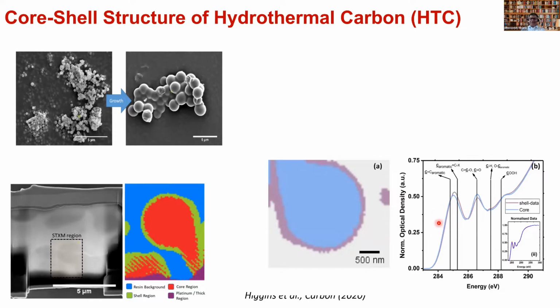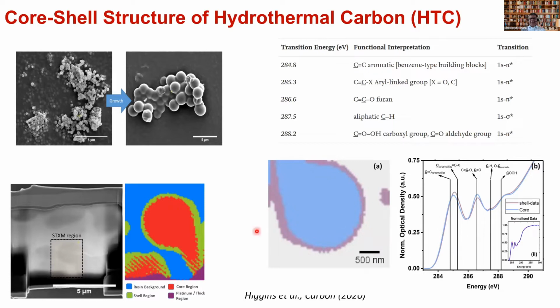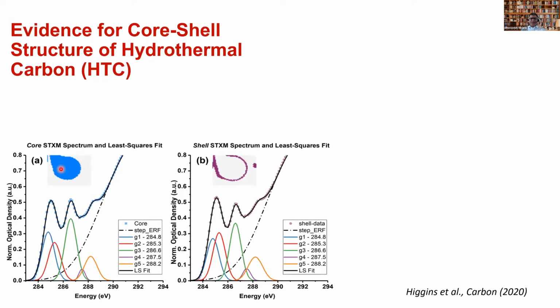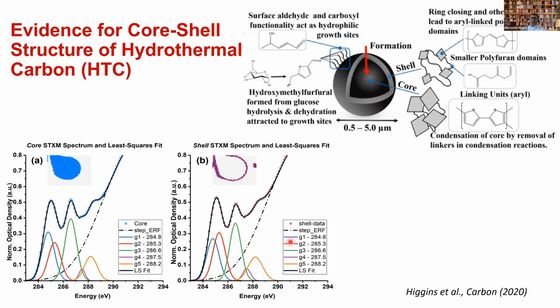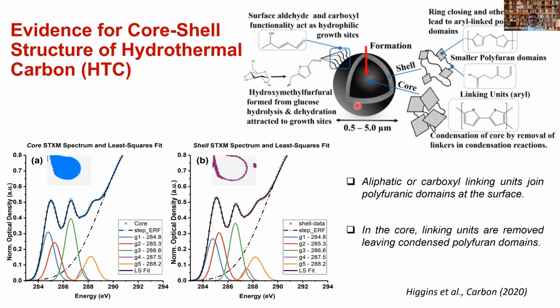Of course, one might say, oh, these are relatively small differences. Of course, in a material which is mostly like 90% carbon, you can't really expect huge differences. But all these differences actually account for some important transitions, as you can see here. More importantly, when we took the core and shell regions and extracted spectra out of those and analyzed them, we found a beautiful picture. The interpretation that came out, in a nutshell, is that aliphatic and carboxyl linking units join polyfuranic domains at the surface, as you can see here. But in the core, linking units are removed, leaving condensed polyfuranic domains. So basically, yes, it has a distinct core versus shell, and the core is different.